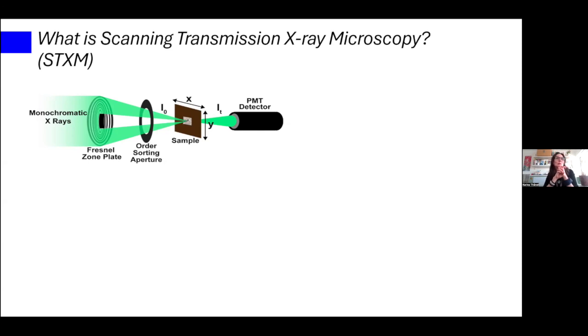Then we move the sample through the beam, and in each spot that we illuminate, we take the intensity of the light that comes through. So basically, we do a pixel by pixel representation of what we get. Then what we get is one image, because we have one energy, we have monochromatic X-rays, and we have mapped out the intensity that comes through our sample.